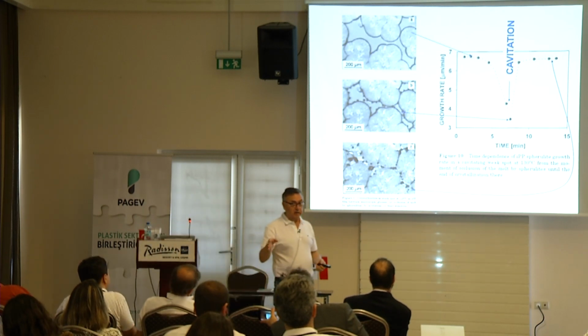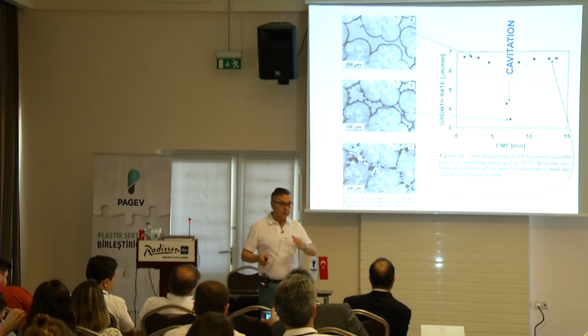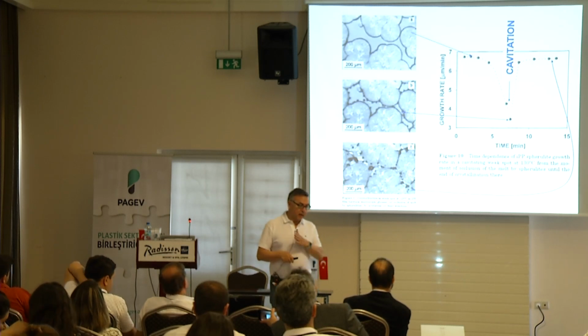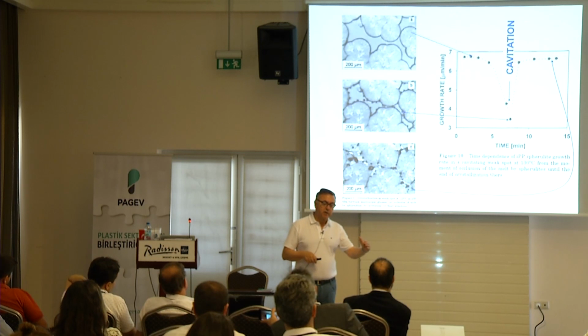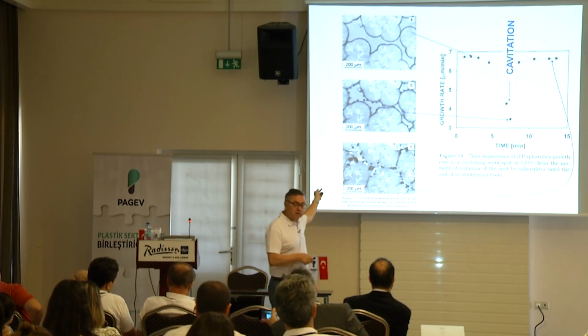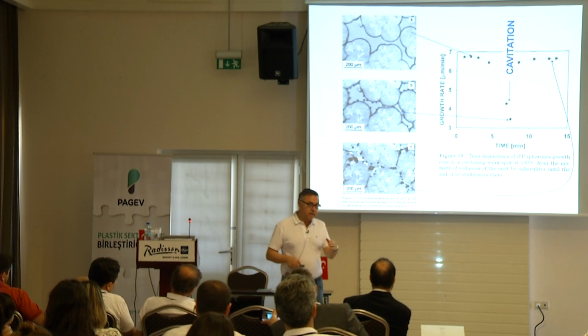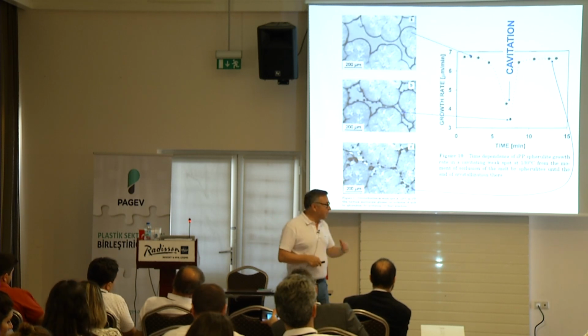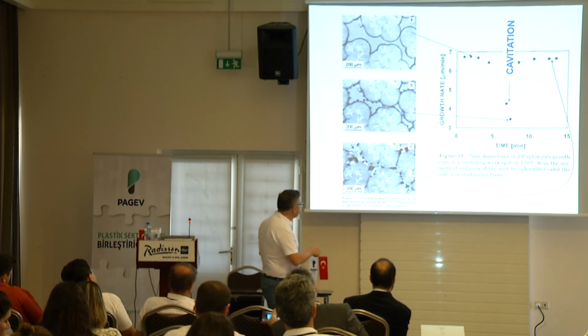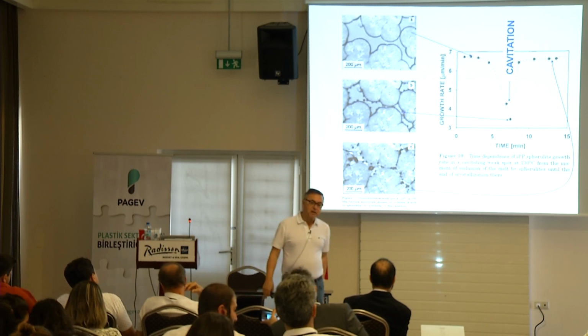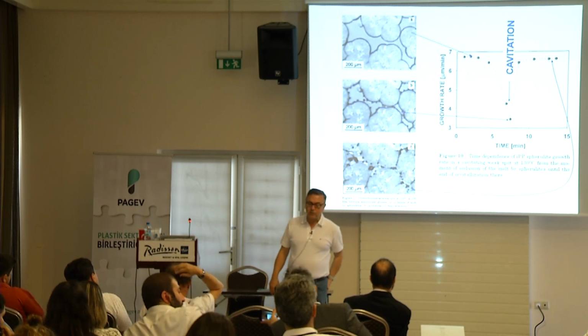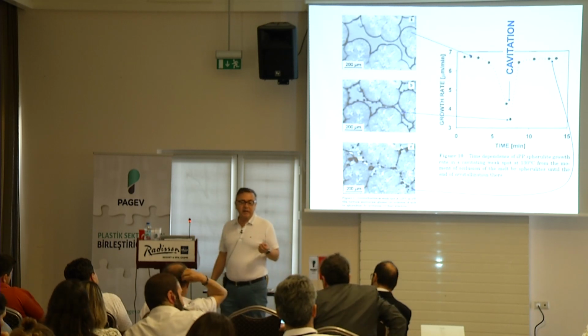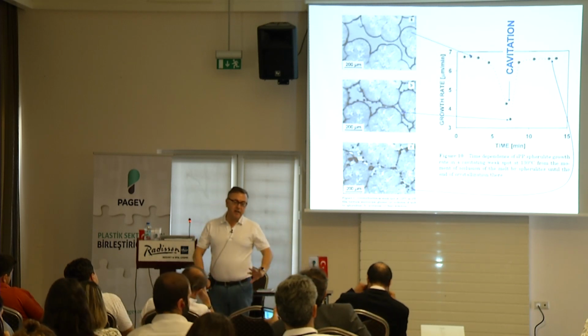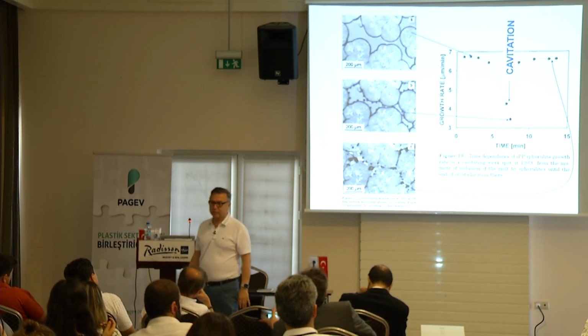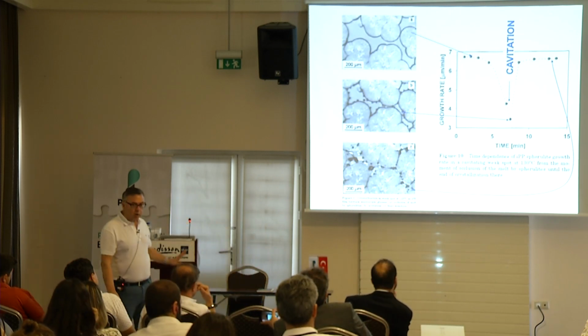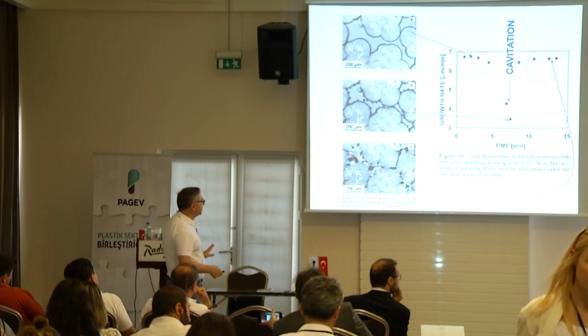This is well known in chemical engineering, where they use crystallization to purify the material, okay? They basically squeeze out all the foreign material to the interface. Well, in this case, what's squeezed out is all the defective material. And if you have defective material basically surrounding the spherulites, your impact strength is going to suffer, right? So again, reducing the size of the crystals homogenizes the material and lessens the issue. It's always there, but it lessens the issue.